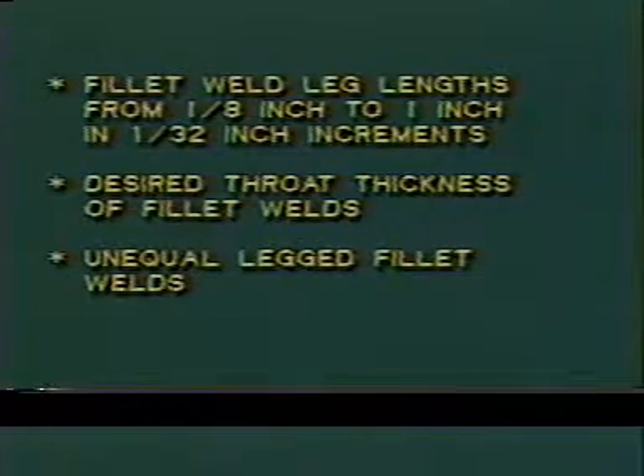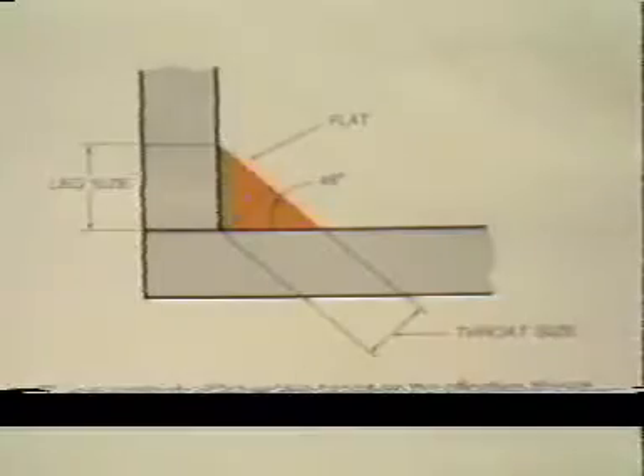And unequal-legged fillet welds. The strength of a fillet weld is based on the effective throat thickness, which is the shortest distance from the root to the face of the weld. For an equal leg, 45-degree fillet weld, the throat is 707 thousandths, which is the sine of 45 degrees times the leg size of the weld.